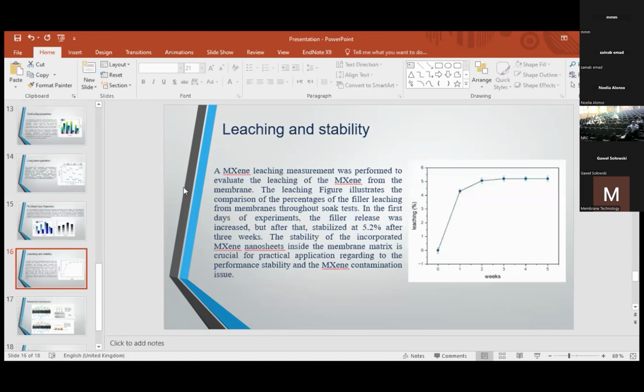Leaching and stability. A MXene leaching measurement was performed to evaluate the leaching of the MXene from the membrane. The leaching figure illustrates the comparison of the percentage of the filler leaching from the membrane throughout the soak test. In the first days of the experiment, the filler release increased, but after that stabilized at 5.2% after 3 weeks. The stability of the incorporated MXene nanosheets inside the membrane matrix is crucial for practical application, regarding the performance stability and the MXene contaminants issue.